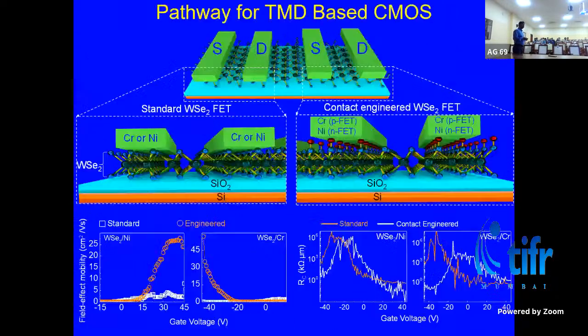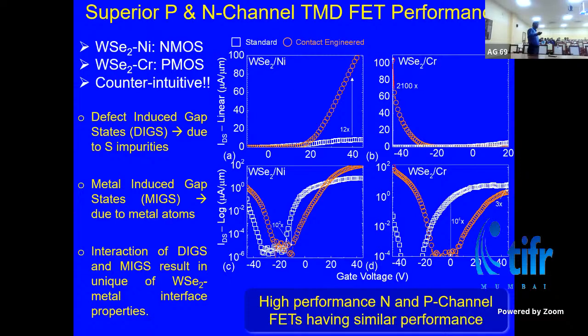Now the question is how to make a P-type transistor. If we choose a different metal along with those vacancies, right? If you choose chrome, you get P-type. You choose nickel, you get N-type. And that's what we demonstrate here. When we chose nickel, we get N-type operation. N-type means when you increase the gate voltage in the positive direction, you have conduction. P-type means when you increase the gate voltage in the negative direction, you have conduction. So we report both N-type and P-type conduction just by changing the metal, but having a sulfur interstitial present. If you don't have the interstitial, it doesn't work, right? Because you don't have those donor and acceptor states present.